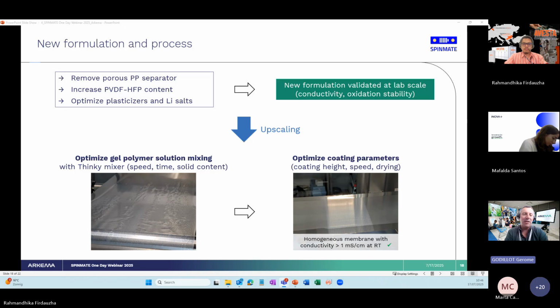We have previous experience at Arkema, and we know that the parameters that you are using for lab scale usually don't work for higher scale, and you always have to optimize them. So that's what we did. We first optimized the mixing part, which is done with the Thinky mixer. We worked a lot on the speed, the time, and also the solid content of the solution. So we ended up with a higher batch, because if you are going to cast several meters, you will surely need a higher quantity of raw materials. So we ended up with a big solution, which was very homogeneous.